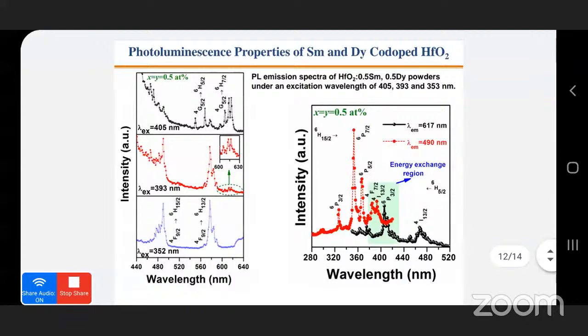So we also examined the PL behavior of the samarium and Dy co-doped system. We can see for low concentrations, like 0.5 atomic percent for both samarium and Dy, when we excite this powder at 405 nanometer, all the PL peaks correspond to dysprosium only. And the 355 nanometer excitation gives us the emission peaks of Dy, and 405 nanometer gives the emission peaks of samarium. And when we excite it at 393 nanometer, we can see that along with the PL peaks of dysprosium, we also observe the samarium peaks.